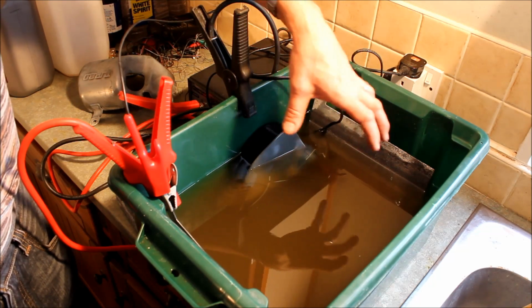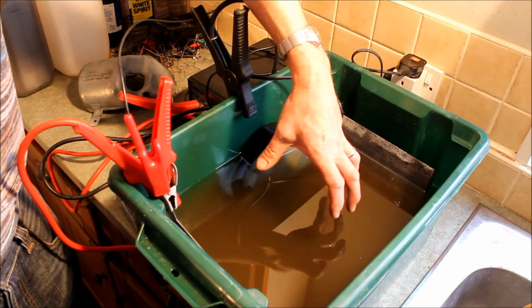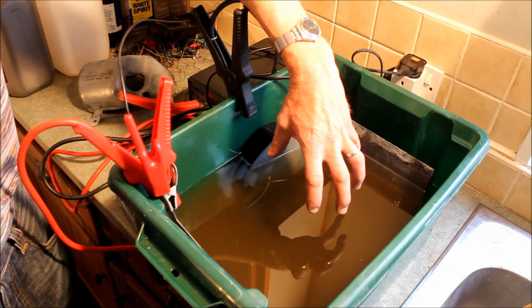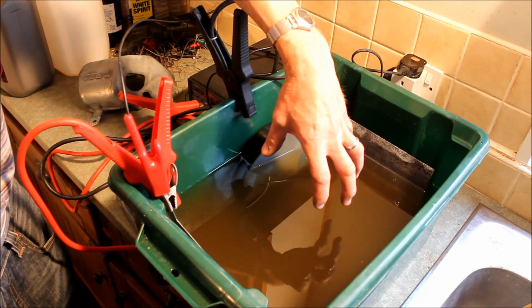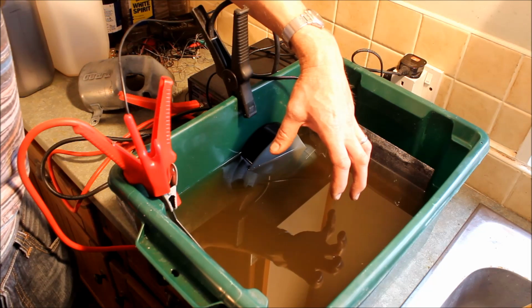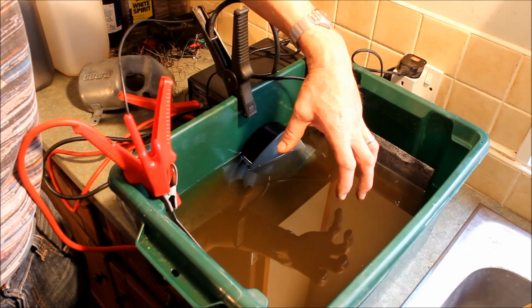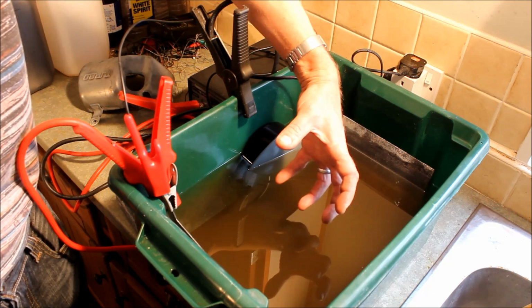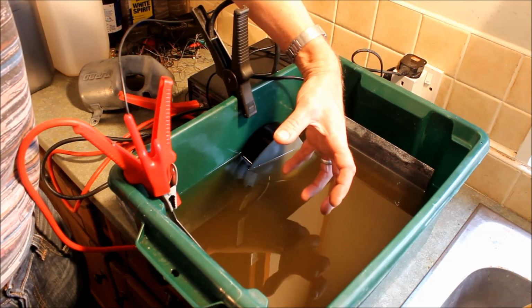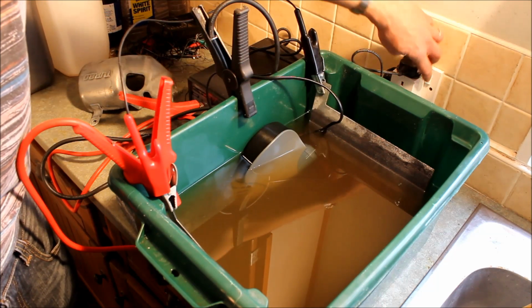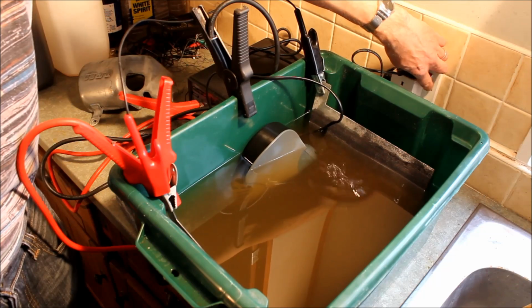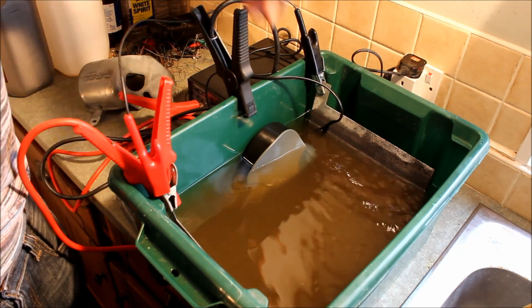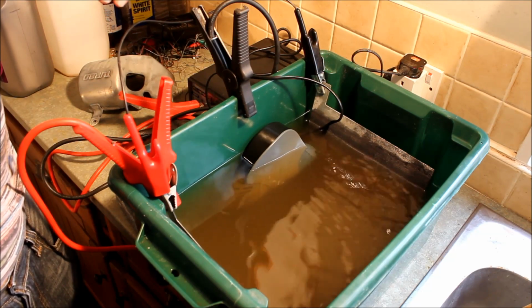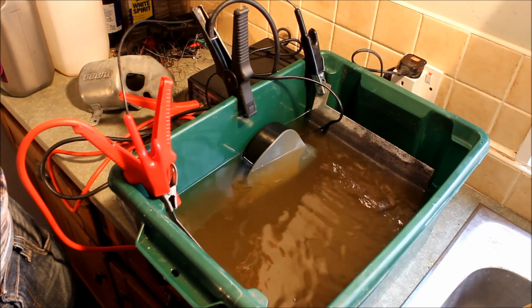The other thing to do is move the part in the bath every 10 minutes or so while it's plating, so you're getting as even a coverage as possible, and also try and position the parts that are difficult to plate, that you're having trouble getting any plate onto, as close to the anodes as possible and facing the anodes if possible. At high currents and high current densities, agitation becomes really important, so really try and get the bath turning over as much as possible. That will help to even out the current density.